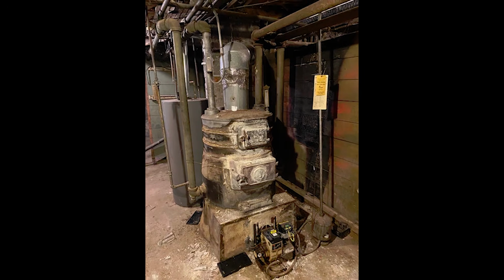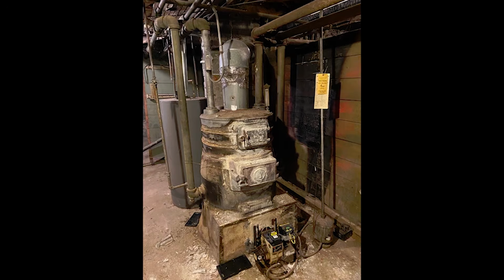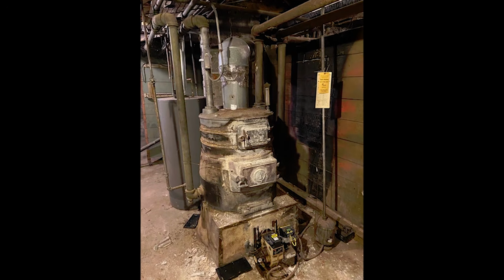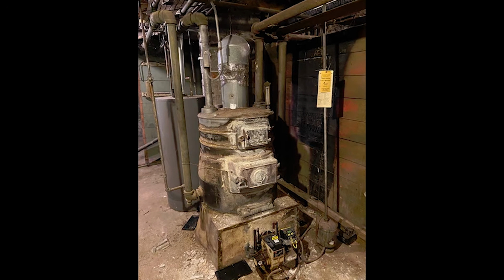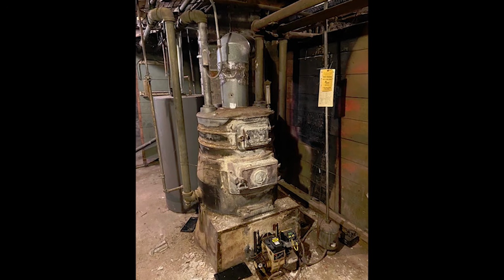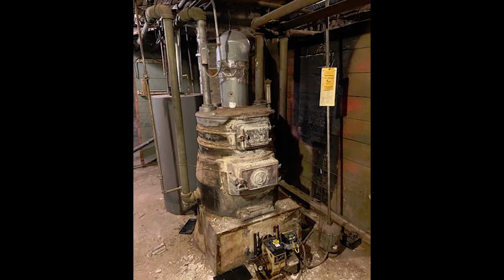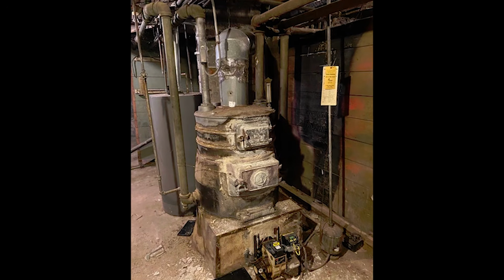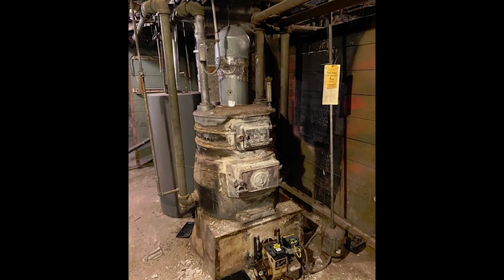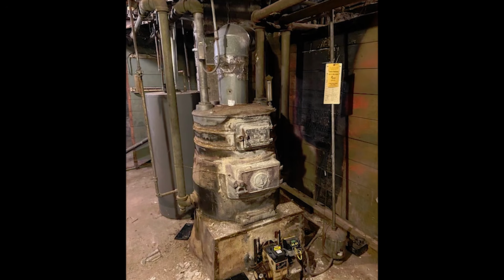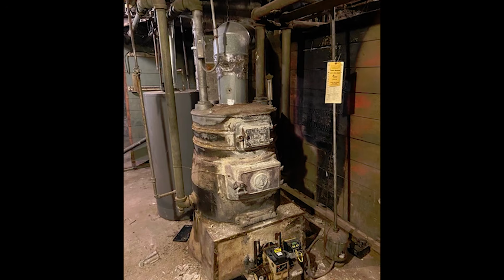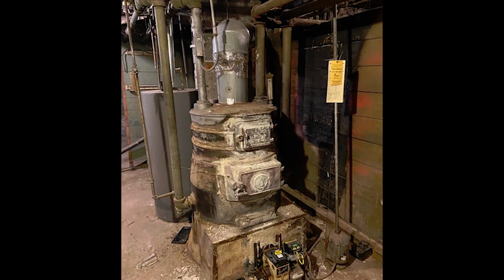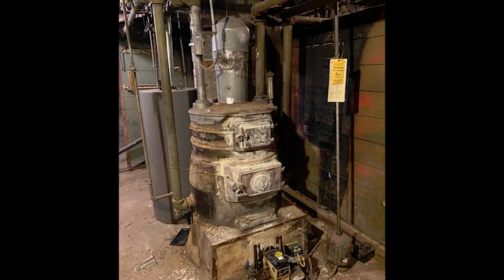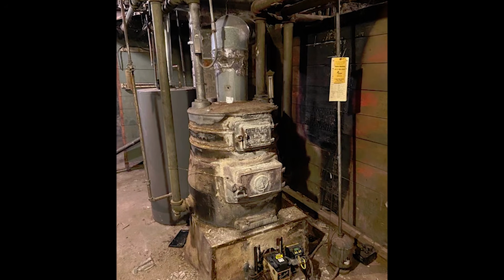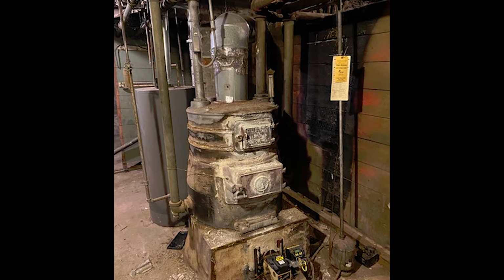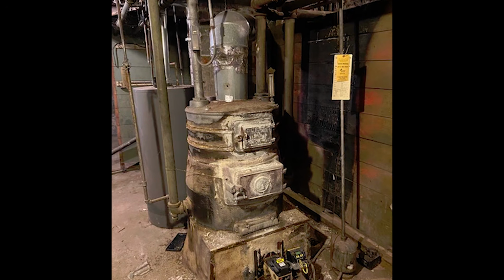The German VDI 2035 standard, which was emerging as European best practice for closed-loop water quality, acknowledged this fundamental conflict. The standard warned that maintaining optimal pH for aluminum in systems containing copper and steel was likely unfeasible, and recommended using demineralized water with very low conductivity as the only practical approach to preventing galvanic corrosion. But demineralized water systems required ongoing monitoring and makeup water treatment that most American building operations were not equipped to provide. Henderson's final laboratory demonstration crystallized the chemistry advantage that American cast iron systems possessed.